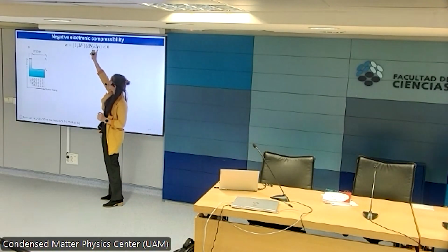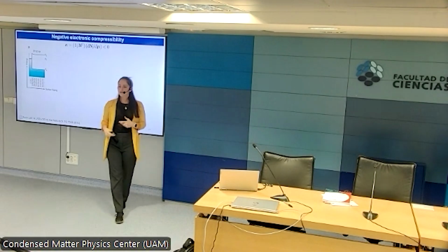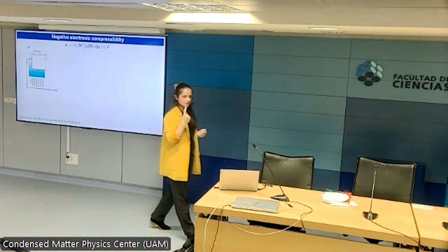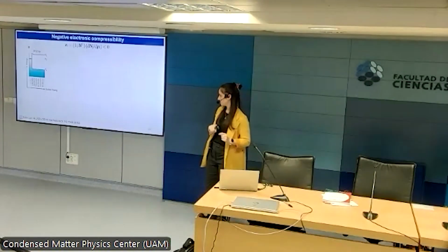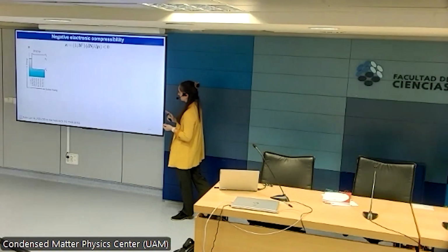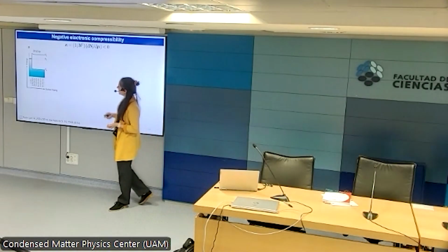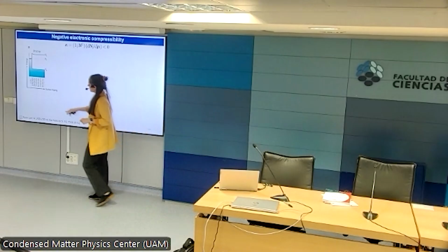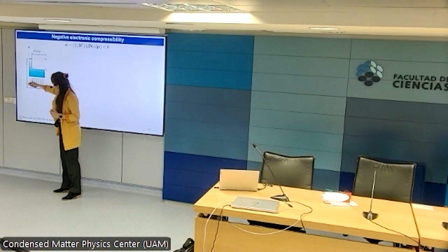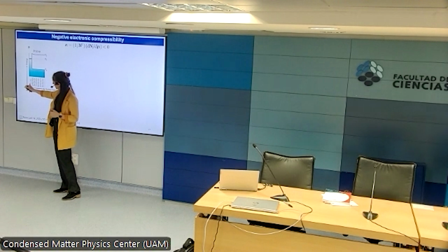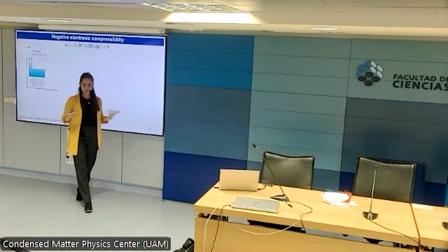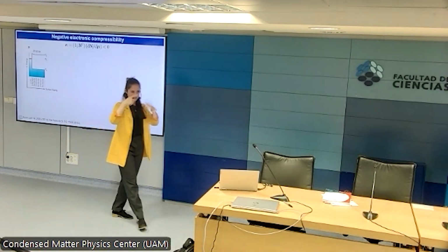This is a lot of fancy words to just say that normally when you add an electron n to your system, your chemical potential mu goes up, so dmu/dn is positive, normally. But in monolayer MoS2, it's been observed that the opposite can happen, so it can exhibit negative electronic compressibility. Explaining it with a band diagram, you have here the bulk of molybdenum disulfide and the topmost layer of molybdenum disulfide. We will treat, for the following, the topmost layer of molybdenum disulfide as an isolated layer, and this is because the van der Waals interaction is very weak.